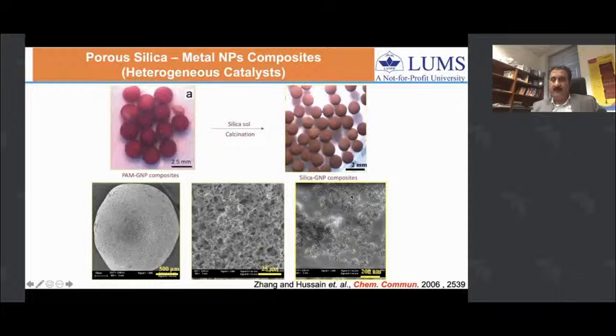In this case, we used 15 nanometer gold particles, but because this is a very generic strategy, you can change the matrix from silica to titania, zirconia, or alumina, and you can also control the size of these nanoparticles, not only for gold, but it also works for other metals as well.